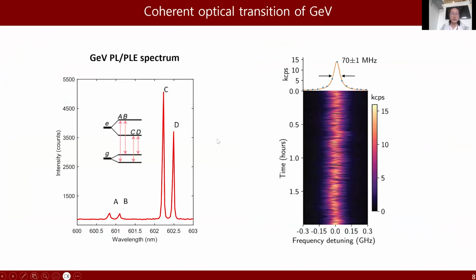From the electronic structure, we know that the GeV should have 4 zero phonon lines, as shown in this PL spectrum. We are particularly interested in the C line, the transition between the lower ground state and the lower excited state. We are interested in this transition simply because it has the highest population. If we want to take a closer look at this linewidth, we can take a PLE scan. We do this by scanning a resonant laser across the C transition frequency and collecting the photons that are emitted into the phonon sideband.